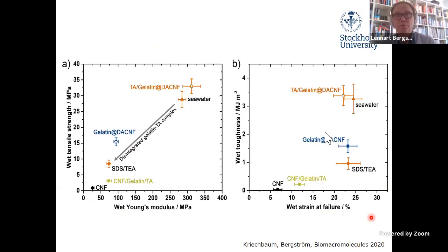It's possible also to recycle these materials, based on well-known properties of tannic acid, gelatin, and protein precipitates. If you put this material into seawater, it resists very well—so a very high ionic strength is not a problem for this material.